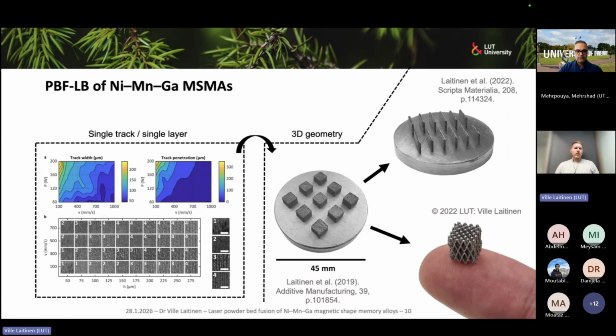How does the process development itself work? The basic track, usually if we start with new materials, is that we do this kind of single track, single layer experiments, just to see where we have a zone of weldability for the material, where we can achieve, for example, crack-free melting of the material, with good wettability of our substrate material, so that we make a really good weld bed without having substantial defects at that stage already. And if we manage to make a process which works in that stage, then we can move to 3D geometry.